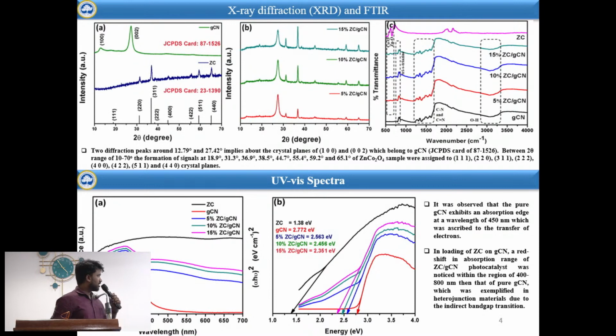So we have confirmed the presence of zinc cobalt oxide and graphitic carbon nitride from the XRD analysis, and the composite has also been confirmed through XRD, where a mixture of phases of both pure zinc cobalt oxide and graphitic carbon nitride is present in the composite sample. Figure A shows the pristine zinc cobalt oxide, noted as ZC, and the upper one, g-C3N4, represents the graphitic carbon nitride. Figure B shows the composite formation in three different percentages of zinc cobalt oxide in graphitic carbon nitride, which are 5, 10 and 15.